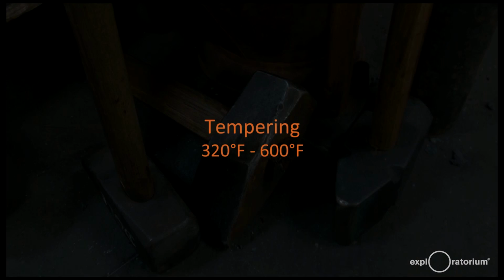To make the quench steel usable, it was tempered, and that means that it was reheated to a lower temperature, somewhere between 320 degrees Fahrenheit to maybe 600 degrees Fahrenheit, which took away some of the hardness, but it also took away the brittleness. And what the tool got in return was toughness and maybe springiness. And so the toughness trades off with the hardness, but you have to hit the right balance for a tool.